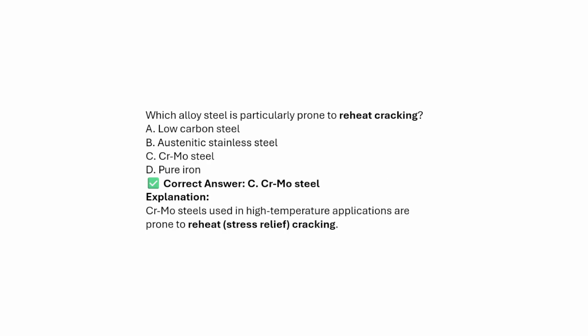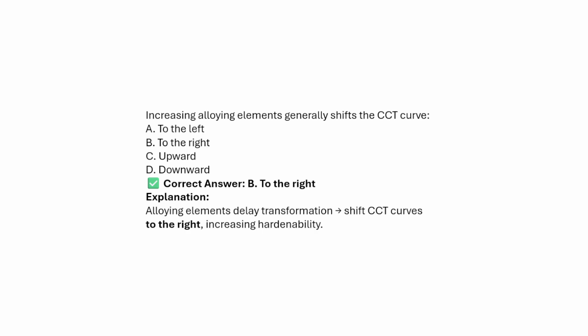Next, which alloy steel is particularly prone to reheat cracking? Is it low carbon steel, austenitic stainless steel, chromium molybdenum steel, or pure iron? The answer will be chromium molybdenum steel. Why? Because chromium and molybdenum easily form carbides in the material. If carbides are formed, it will be more prone to cracking. Chromium and molybdenum steels are used in high temperature applications and are prone to reheat and stress relief cracking.